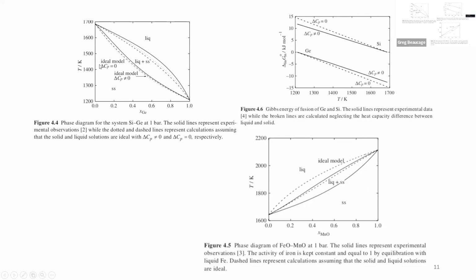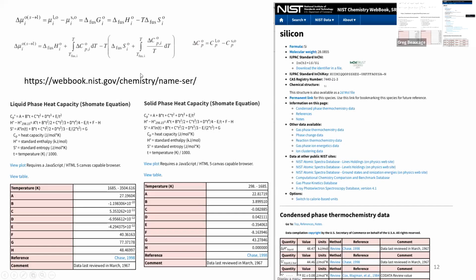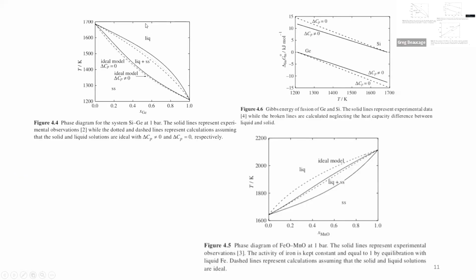They're just spheres, essentially marbles. So this should work, and this shouldn't work. There's some slight deviation that you can account for, like adding a heat capacity term to go from the ideal heat of fusion, at whatever temperature silicon and germanium melt, to the actual temperature where you are. So this integral would be from about 1680 to wherever you are, down to like 1400, to get the heat capacity change for the material.